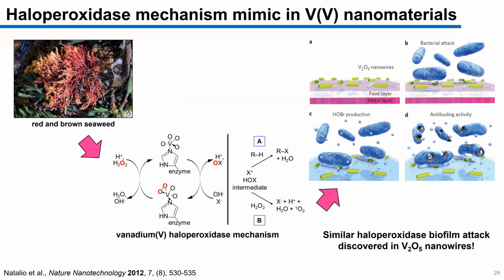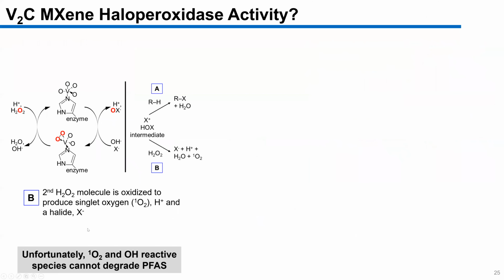And we're not the first to suggest this. There's a study by Natalio et al. that observed a similar mechanism for vanadium pentoxide nanowires in particular, applied to a surface. When hydrogen peroxide was added and bromide was added to the system, they did observe an anti-fouling activity or biofilm defense mechanism occurring on the surface because of a mimic of the vanadium haloperoxidase enzyme. So here's that mechanism again.